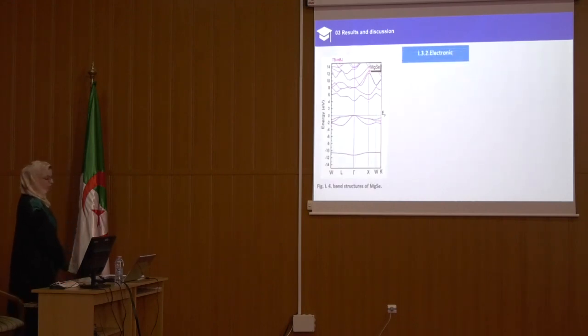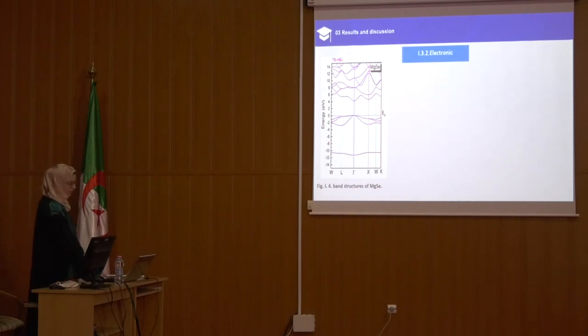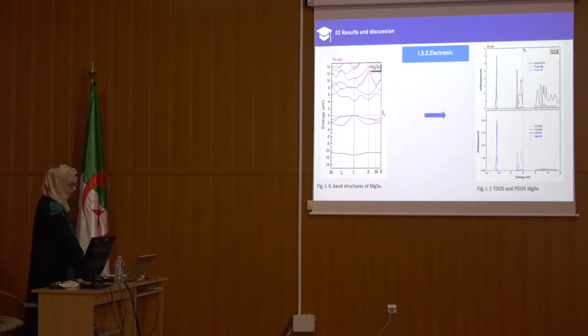For the electronic properties, in the case of zero concentration, meaning we have MgSe, we can see clearly that MgSe is a non-magnetic semiconductor. The Fermi level is set to 0 and indicated by the dashed line. We can see that this compound has a direct band gap semiconductor in the gamma direction.